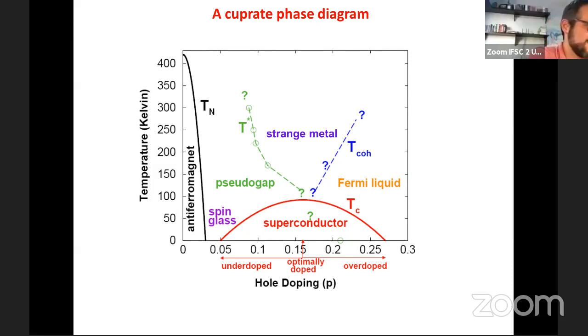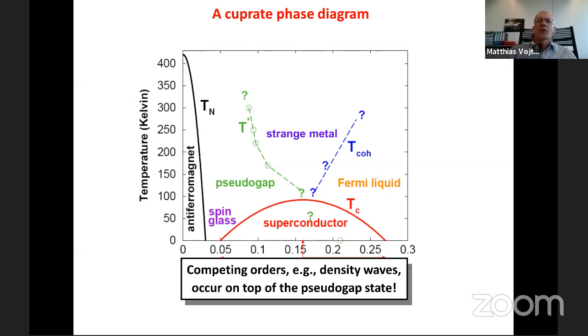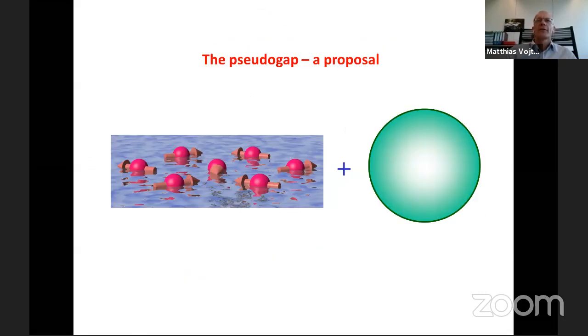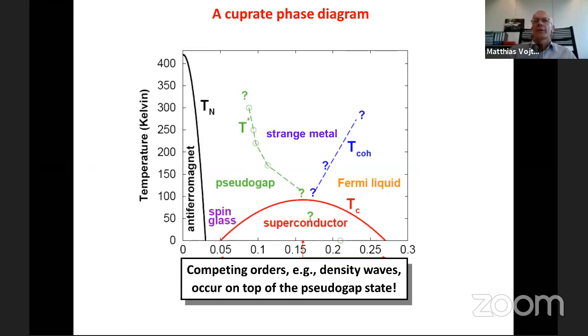That's an interesting question, and it's getting complicated. First of all, the properties of the spin glass are not universally the same across all cuprate families. The spin glass certainly is a local moment spin glass, and that is compatible with the idea which I advocated, namely that the underdoped state is a state of this type. So you have local moments which coexist with charge carriers. And the local moments, in the presence of this order, can in principle show an instability to a type of spin glass order. Again, whether or not a strong spin glass is realized depends on which cuprate family you look at.